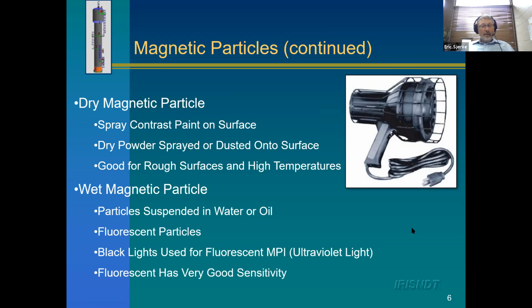So with wet magnetic particles, we use the same iron oxide as the magnetic particles, but we put it in an oil or a water, and it's fluorescent. So this has to be done in the dark, and then we use an ultraviolet light to visually see the defects. So wet magnetic particle is more difficult to do because you can't have light and it can't be done at high temperatures, but it's more sensitive. And in NDT, sensitivity is the ability to see small defects. So it has better ability to see small defects.